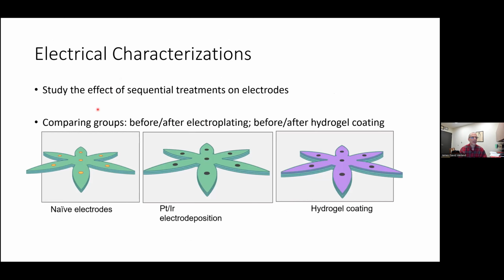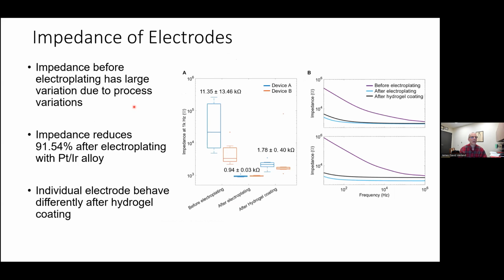So what we did then to characterize this device is we looked at the effect of sequential treatments on the electrodes. There were the naive electrodes without any treatment, the electrodes after platinum iridium deposition, and then the electrodes after we coated the hydrogel. We needed that PDMS layer in order to bond with the hydrogel, so that's why we followed with a PDMS layer on top of the polyimide. And what we found is that before electroplating, there was huge variability, and we attribute this to some lack of cleanliness of the gold electrodes, and also PDMS contamination on the electrodes.